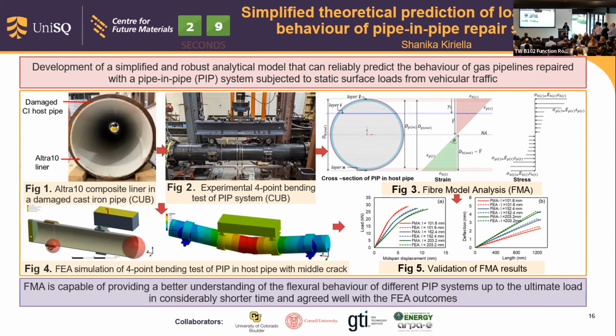Therefore, this study aimed to develop a simplified analytical model that can reliably predict the behavior of PIP systems subjected to lateral loading. The theoretical model of the 4-point bending test was modeled using fiber model analysis, considering the nonlinear material behavior, and validated using finite element and experimental results. The research revealed that fiber model analysis is able to provide a better understanding of the flexural behavior of PIP system in a considerably short time period and agreed well with the FEA outcomes.